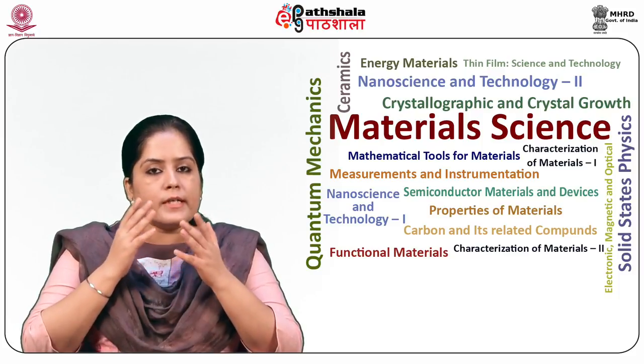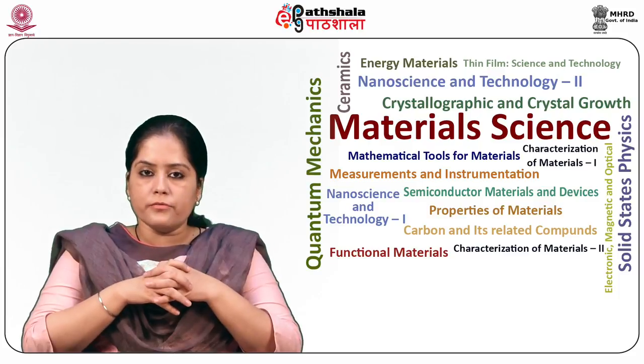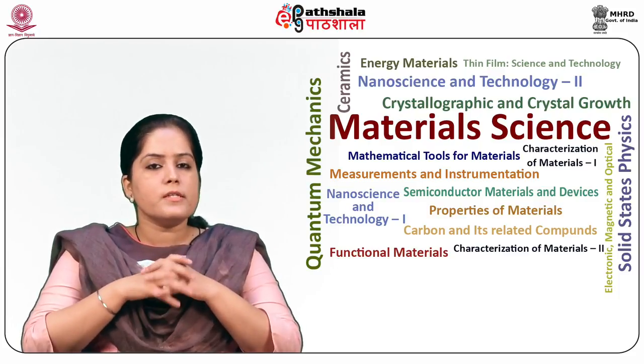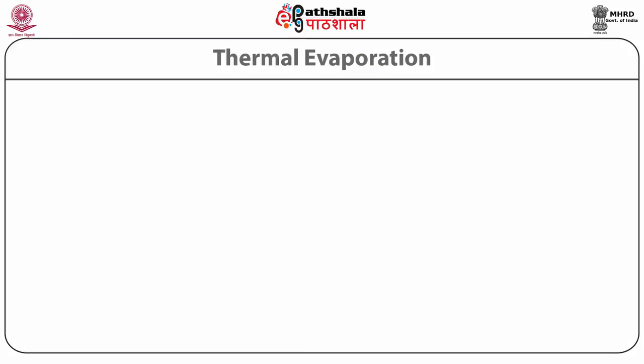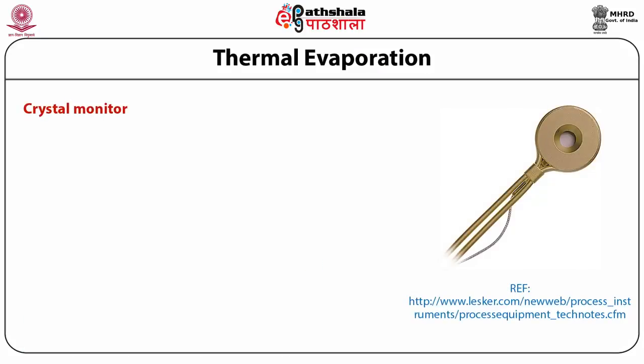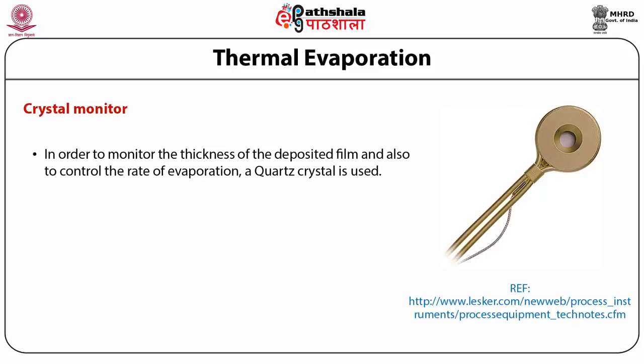We get the poor density and adhesion of the film. Step coverage is harder to improve. Crystal monitor. Now, in order to monitor the thickness of the deposited film and also to control the rate of evaporation, a quartz crystal is used.